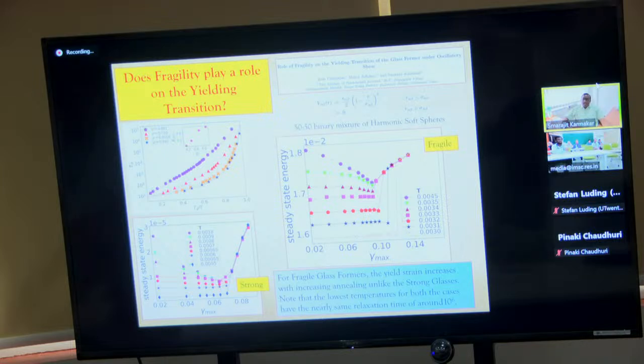But the point at which you yield remains very similar, even if you increase your annealing. If you go to lower and lower energy states, or better annealed glasses, your yield point does not shift. At the same time, if you look at glasses formed from these fragile liquids, at density 0.943, and look at the same phase diagram as a function of the oscillatory shear amplitude, what we see is that the yield point moves significantly with increasing annealing. So as you go to lower and lower energy states, your yield happens typically with a shear band formation, but at a strain which is much larger than what you get in the poorly annealed glass.